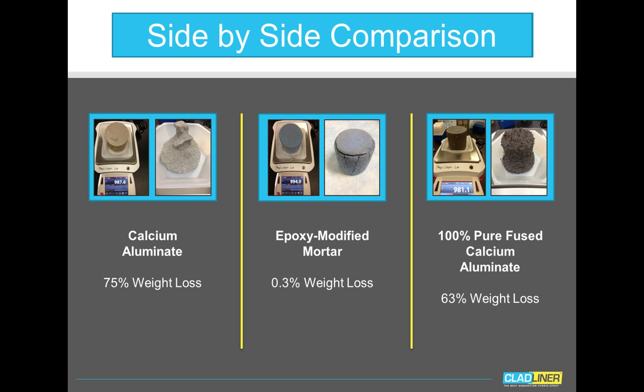So when we do a side-by-side comparison, let's look at what we actually found. Okay, the calcium aluminate lost approximately 75% of its weight after the 7-week immersion. The epoxy modified mortar lost 0.3% of its weight, and the pure fused calcium aluminate lost 63% of its weight.